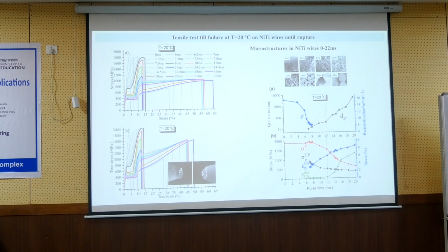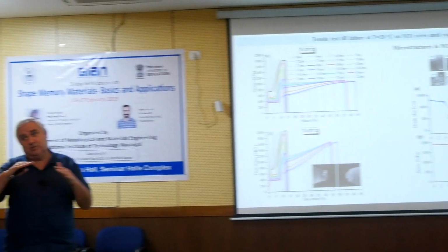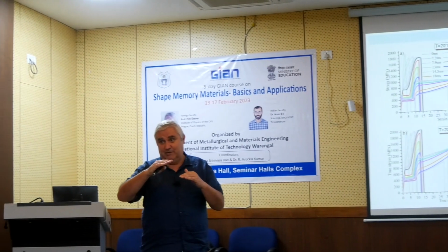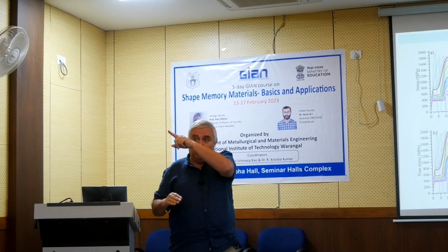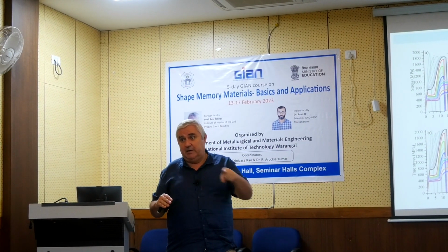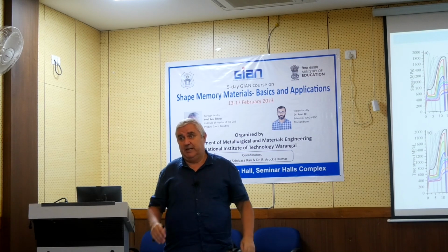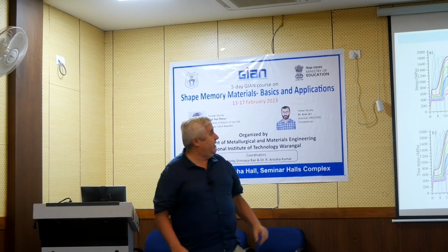And then I perform maybe heating, cooling under constant stress. This is also heating, but heating only to maybe 100 Celsius and cooling to -50. And for this, we use Peltier. We never use electric current because we cannot have active cooling. But with Peltier, we can control the decrease of the temperature in time to be linear with Peltier element. And this furnace,